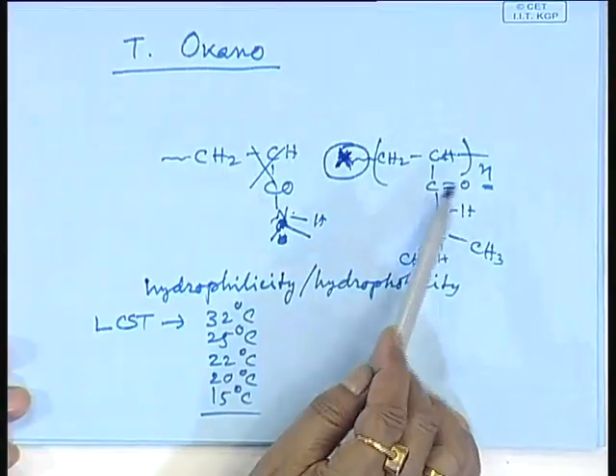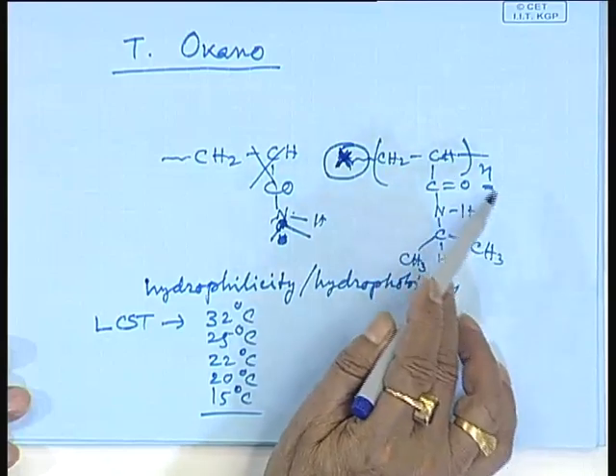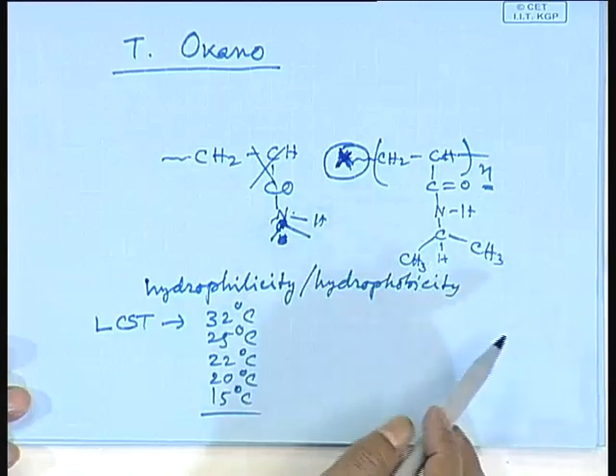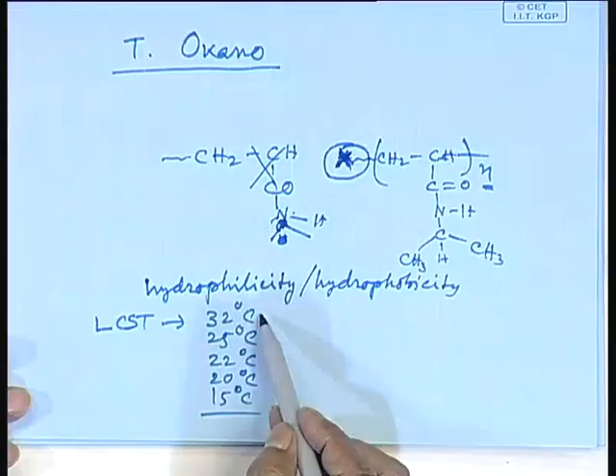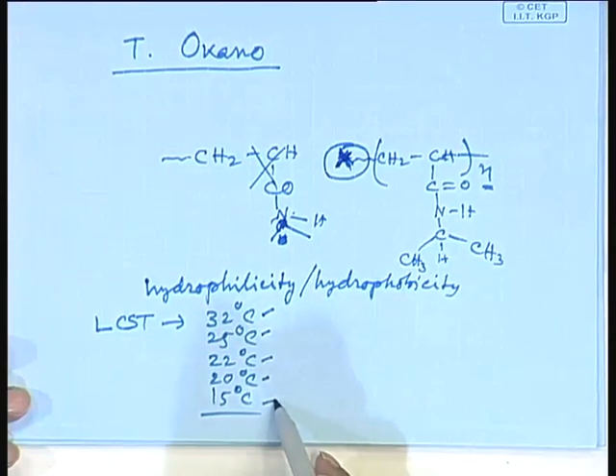That depends on the frequency of this group. That means, if you make a copolymer of this monomer with another monomer, say butyl methacrylate or ethyl methacrylate, a certain percentage of butyl methacrylate monomer is polymerized with N-isopropyl acrylamide monomer, or a certain percentage of ethyl methacrylate is copolymerized with this N-isopropyl acrylamide. So, by controlling that copolymer composition, we can have a variation in LCST as we require, because it is not always possible that in all devices, in all applications, only one transition temperature will show this transition. No, it is not necessary, it is not possible also, it is not required also.